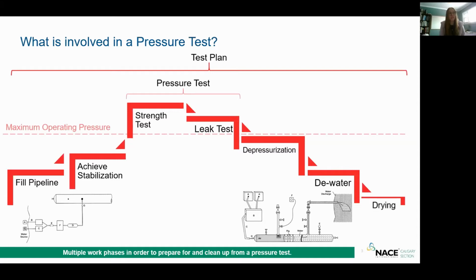And in the event relative to the maximum operating pressure, this can sometimes be greater than 150% of the maximum operating pressure, and can be seen at points throughout the line. To put it in further perspective, these pressures are sometimes greater than what's experienced in the steel mill, and even greater than the specified minimum yield strength, or what we refer to as SMYS, of the pipeline. CSA allows, depending on material, of course, up to 110% of the specified minimum yield strength to be reached. And we'll go into what you need to do in those cases next.